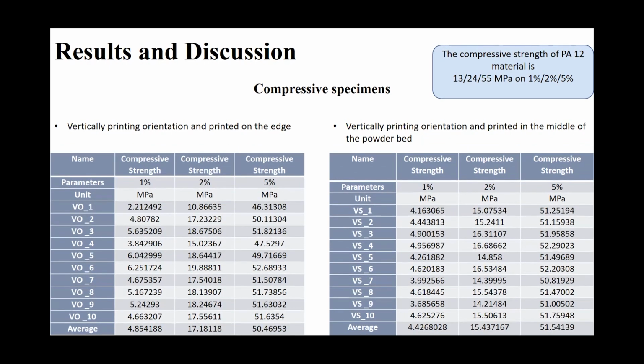Similar to horizontally printed test specimens, the vertical specimens also obtained values that are quite different from the compressive strength of PA12 material. The smallest deviations of compressive strength values were observed for vertically printed specimens in the middle of the powder bed. And the compressive strength value of the vertically printed specimens in the middle of the powder bed is 3 megapascals lower than the compressive strength value of the PA12 material.